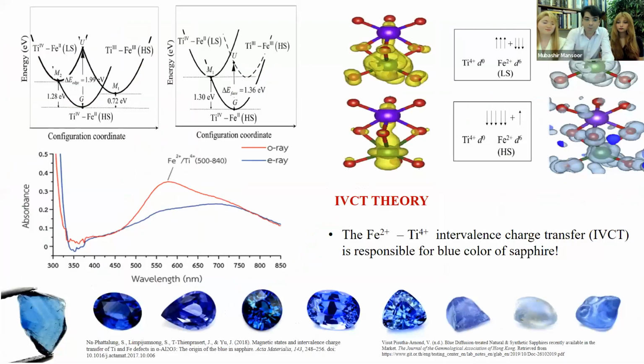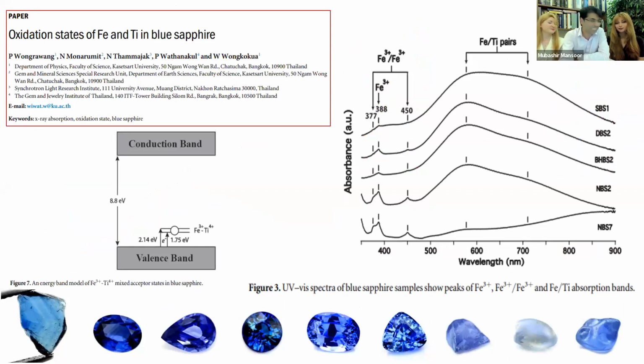Okay, there was this beautiful theoretical study that was published by Professor Patalong in Thailand, and they had even calculated very beautifully how the energies are in this respect. And it turns out that they can reproduce the UV spectra of a blue sapphire just by considering this iron and titanium sitting side by side. So it's very good foolproof information that iron titanium intervalence charge transfer is the cause for blue sapphire. But believe it or not, this is not the only thing. Exactly, it's not the only thing.